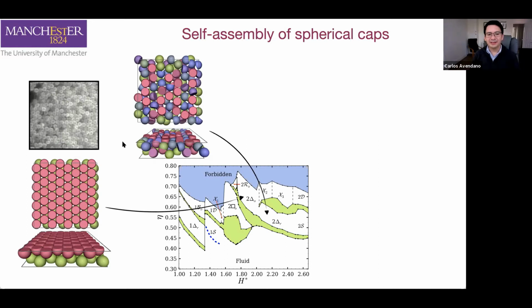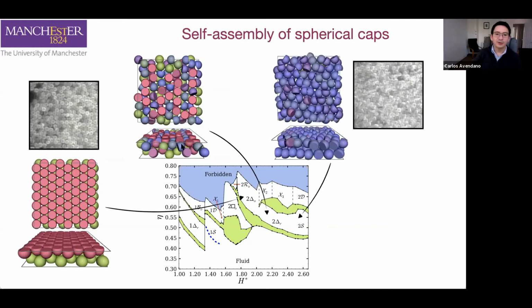But the difference with this structure on the left-hand side is that now the particles actually can rotate. So this is the example of a plastic crystal in which the center of masses are completely localized in specific lattice sites, but the particles can adopt any type of orientation that they want. And if we keep increasing the distance between the plates, now the particles again will try to adopt the side orientation that was observed in the monolayer. And that again is completely in agreement with experimental systems.